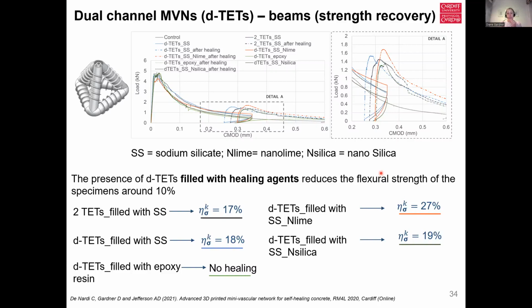Especially in systems such as the vascular network systems, which we can provide quite a bit of pressure to ensure it flows. So actually achieving about 20% with these minivascular networks is actually good going. We see very little difference between the two minivascular networks with sodium silicate and a dual channel minivascular network with sodium silicate. So there's very little difference between those results. What we can see is that the simultaneous presence of nanolime and sodium silicate at the time of damage has promoted the formation of calcium silicate hydrate and thus resulted in an enhanced healing performance. And that is about 27% that we can see on the screen here. We didn't see the same sort of effect with the dual channel TETs filled with sodium silicate and nanosilica. And again, we're approaching what we would expect to be our ceiling value for minivascular networks with a sodium silicate solution inside.